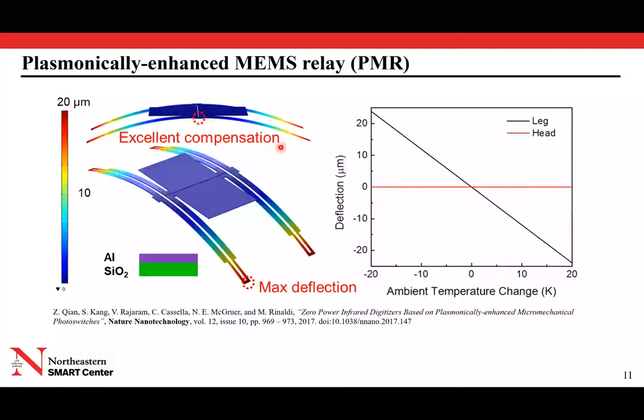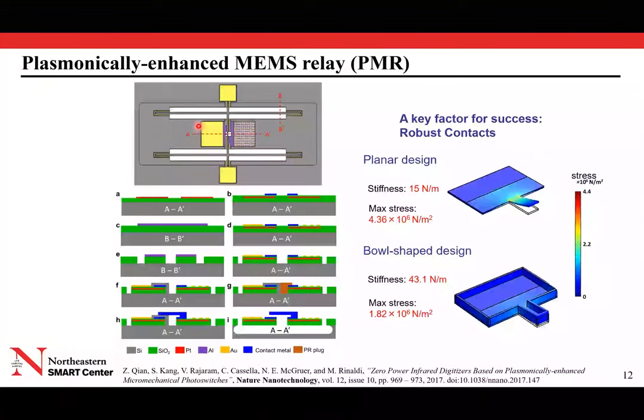So as you can see here, for example, if you have an ambient temperature variation, both the inner and the outer legs of the structure will bend in the same direction. And that will basically translate in a near zero relative displacement of the two heads. So there is no modulation of that contact gap.